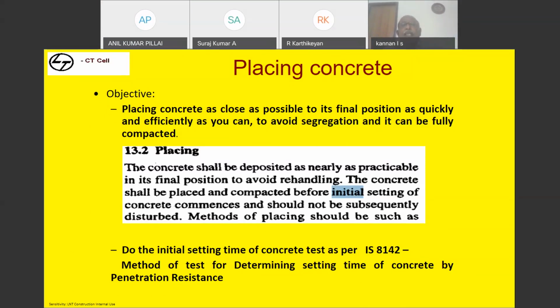That means, suppose I'm making a concrete, the initial setting time of concrete is 4 hours. I can handle the concrete up to 4 hours, provided the concrete mix design has the required slump up to 4 hours, what is needed for the concrete to handle and place. It is not that I can retemper the concrete, add water, and make it last up to 4 hours. My initial setting time is 4 hours, not that. So if the workability is achieved, the code says to this extent we can make it.